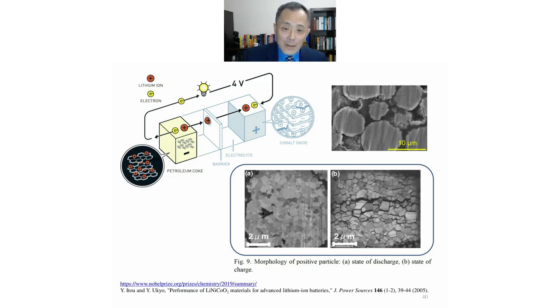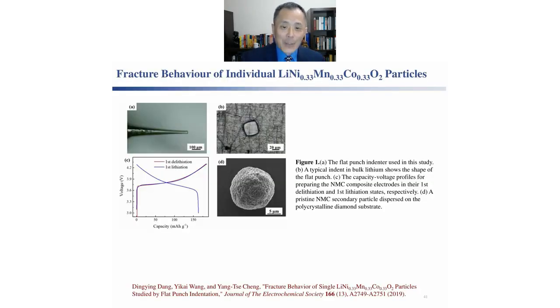So we wanted to measure how severe the mechanical damage can be by performing indentation on individual particles. In this case, it's a lithium nickel manganese cobalt oxide particle. We can first introduce lithium into the particle by cycling the electrode to a different state of charge, and then take the electrode out, dissolve the electrode, the binders, and harvest the individual particles. Using our flat punch indenter, we can do single particle compression measurements.